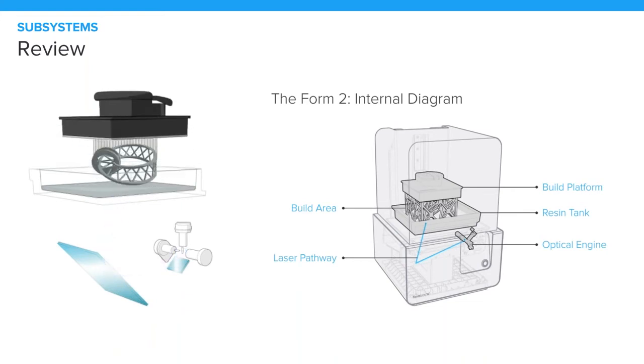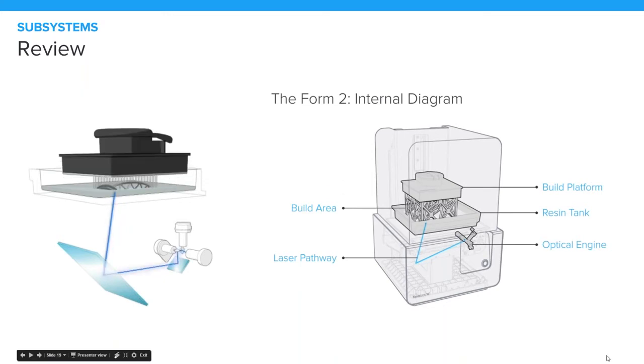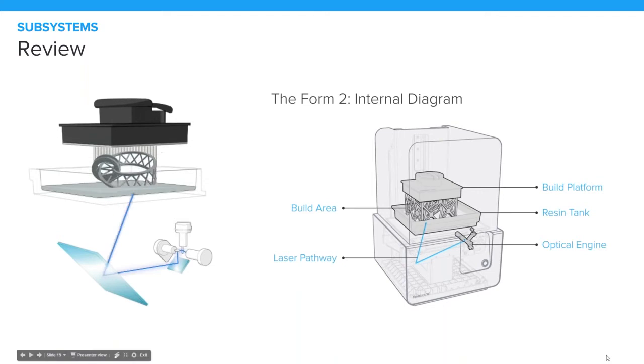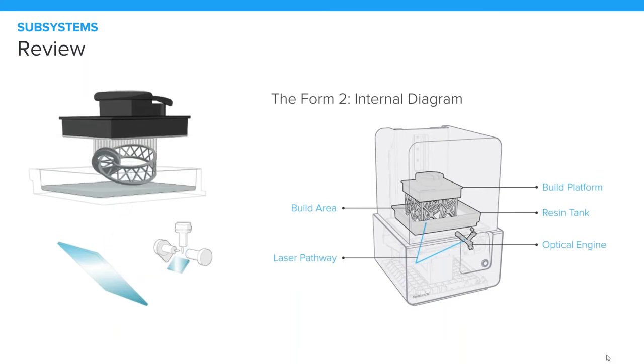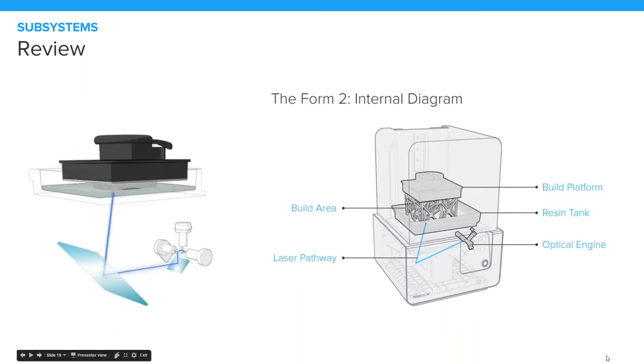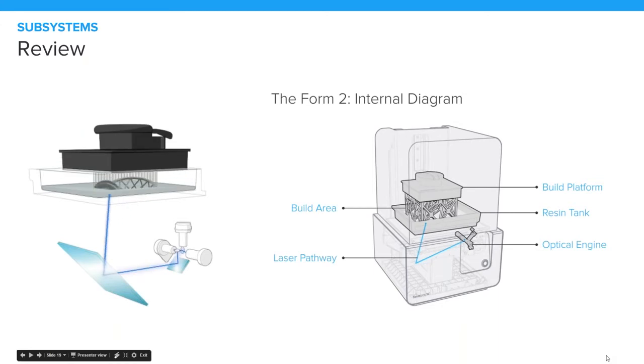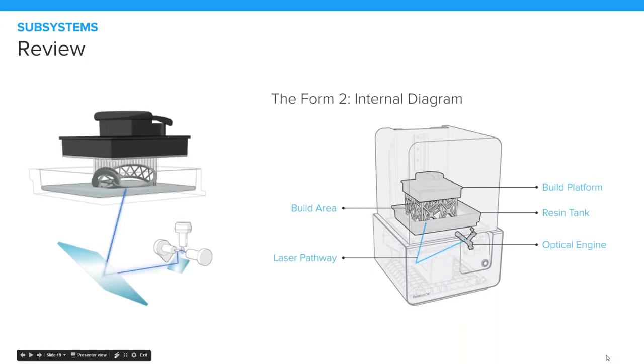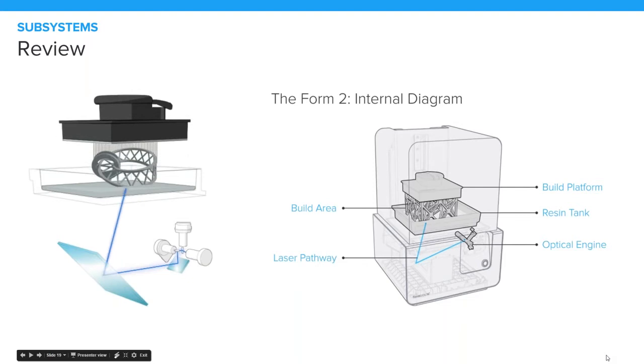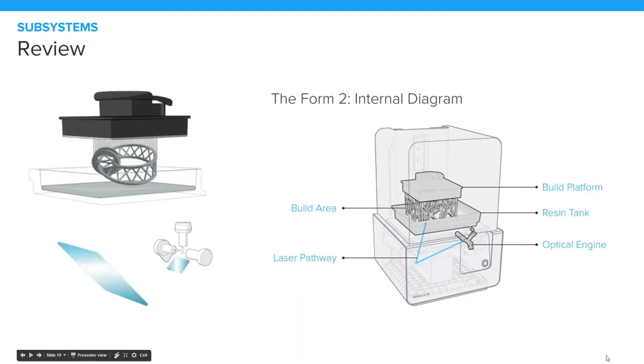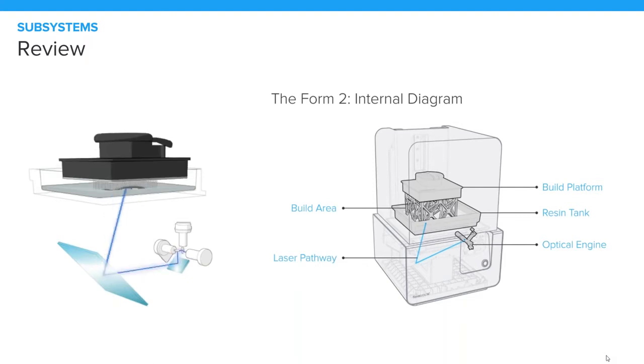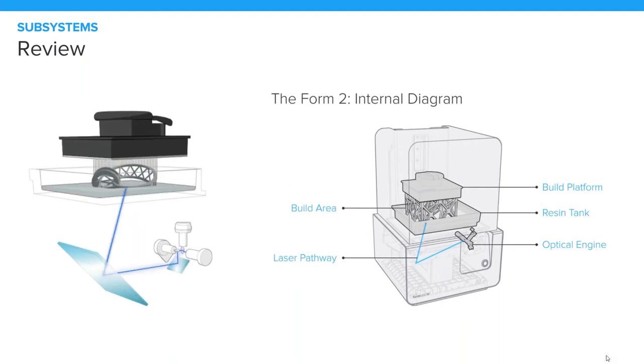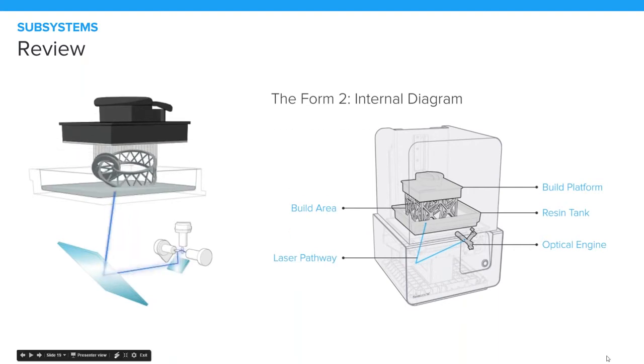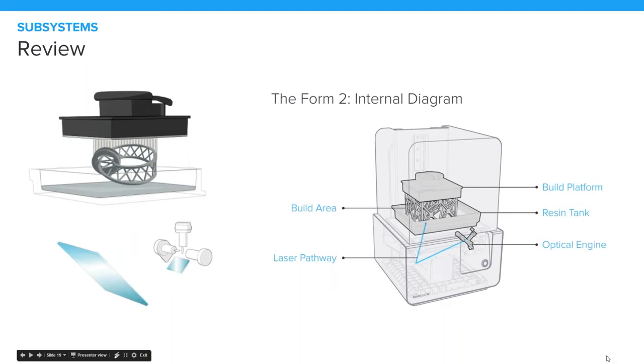The laser hits the bottom of the resin tank and cures the resin in a gradient, radiating out from the center of the laser's focus. That means that layers transition more smoothly into each other and are not stepped, which affords us that smooth finish that's typical of SLA parts. Then the sliding mechanism peels the part off the bottom of the tank so that the build platform can raise up and allow the wiper to slide across. The wiper's primary purpose is to mix up the resin and aerate the PDMS, thus reducing peel forces.